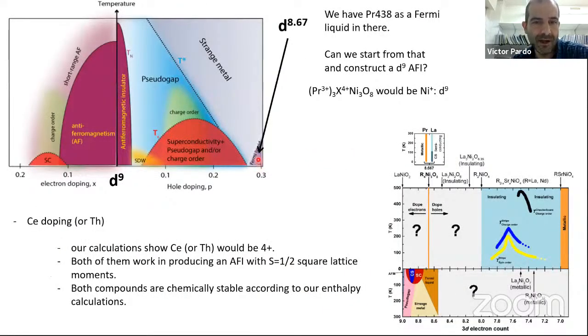We already are here with a nickelate that is a metal. So this would be this praseodymium 438. So we said, okay, well, how can you move it? We need to dope it, and dope it with the correct physics. So we said, okay, you can introduce here a cation that is 4+, so that the electron count would be nickel plus d9 if you introduce it in, let's say, 1 out of 4. So if you introduce praseodymium 3 cerium nickel 3 O8, that would be the correct electron count for being here.